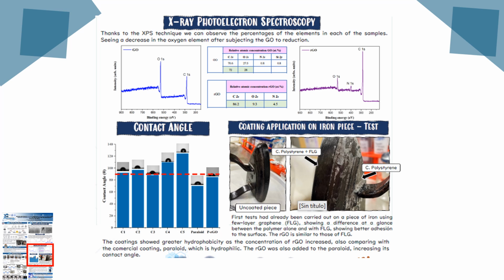At the beginning of the project, a small test was done with few-layer graphene, FLG, applied in the same way on a sheet of iron. We can see the polystyrene alone easily comes off the surface, but the polystyrene FLG does not. It has good adhesion and visually a good coating.